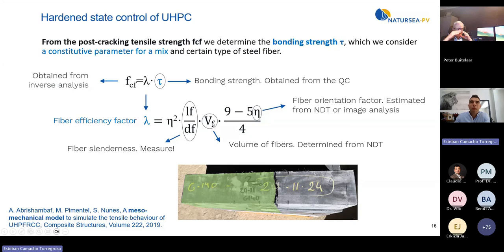Until now, we knew the volume of fibers that we have in the batch, but now with the device that I already showed you, we can determine the volume of fibers that we really have in the element that we tested, so we can be much more accurate. And third, the fiber orientation. The fiber orientation can also be estimated with the device I already showed, and I am going to show how. So we can obtain the fiber efficiency factor for the element we are testing.